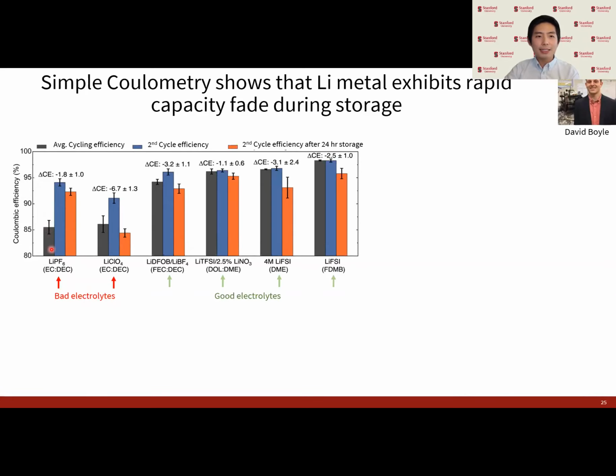So this black bar here is the average Coulombic efficiency, with higher being better. This blue bar here is the second cycle efficiency if there is no rest step. And this orange bar here is the second cycle efficiency if you include a 24-hour storage period. Now this delta CE value here measures the drop in cycling efficiency when you include this storage step. And what you can see is that there are bad cycling electrolytes with better storage efficiency, along with good cycling electrolytes with moderate to bad storage efficiency. But the two best electrolytes in the literature, this dual salt and this FDMB electrolyte, have fairly bad storage stability.